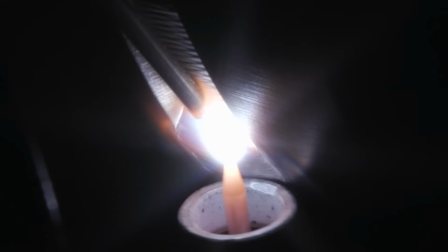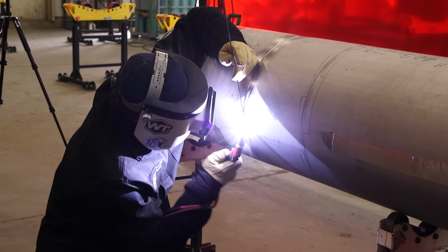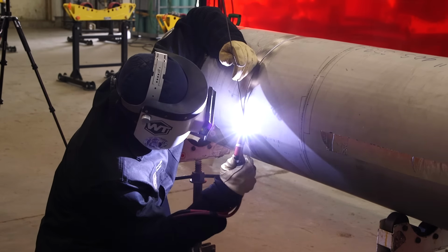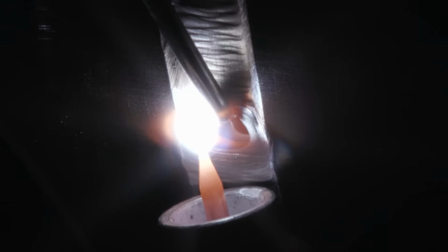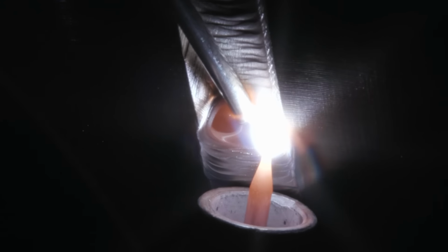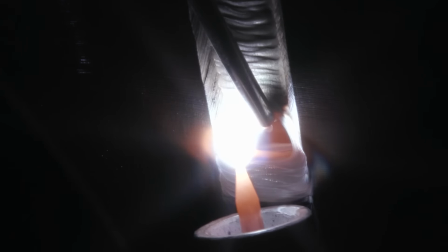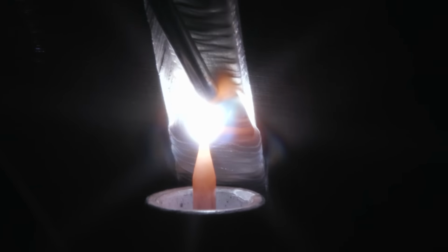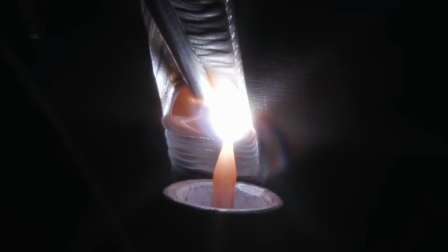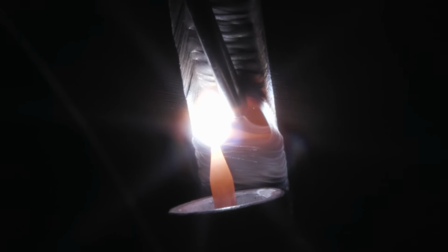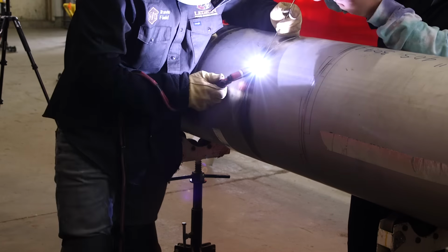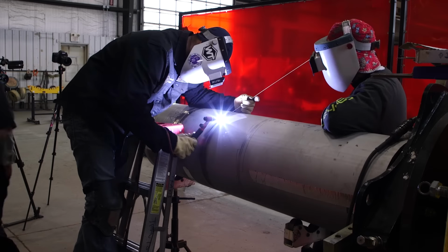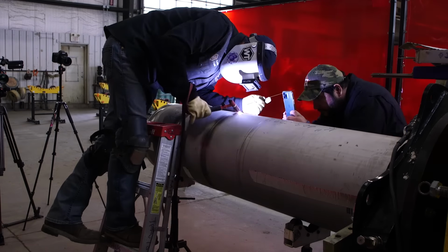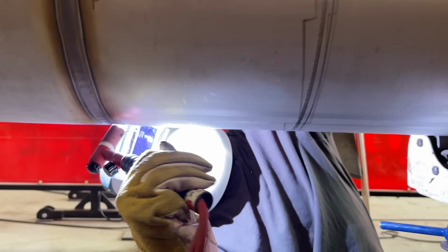The weld puddle is very, very glossy and clear, very shiny. There's no oxides being pulled in on the piping itself. You can brush those oxides off. You'll see those oxides pretty badly with the nickel alloys getting pulled into the weld puddle, but the stainless is just a nice, clean glossy weld puddle. Just controlling the rate of solidification of the weld puddle here just by how much of the filler metal, being a solid mass, the weld puddle needs to break down.